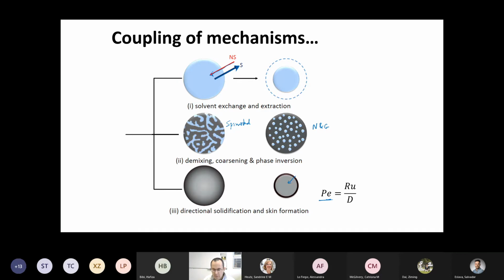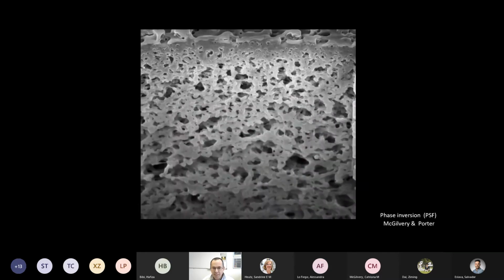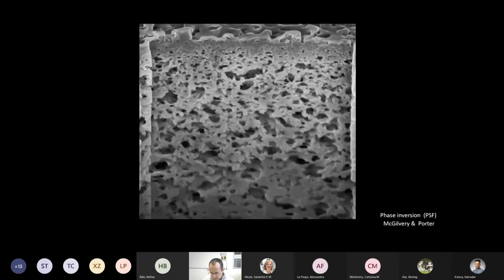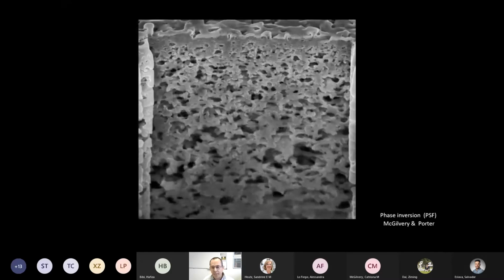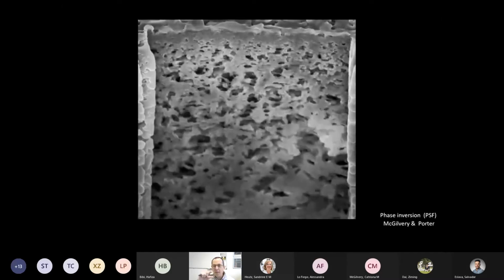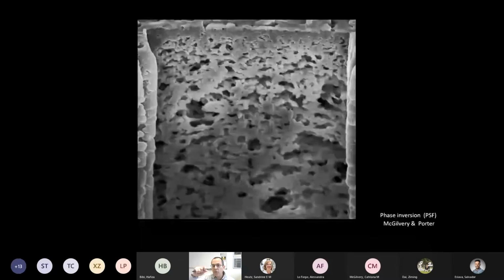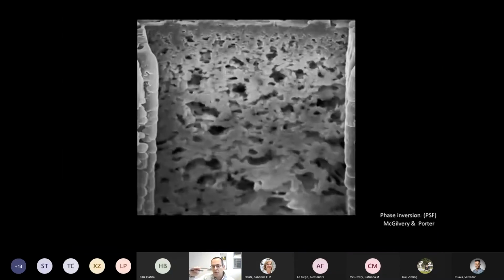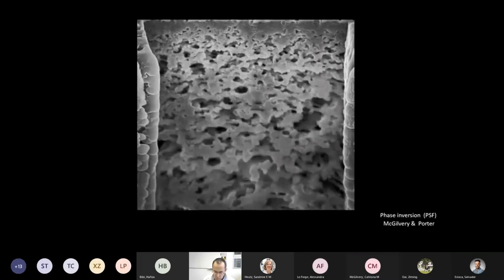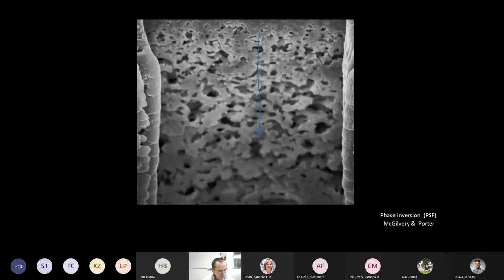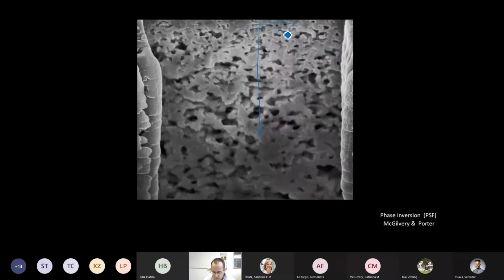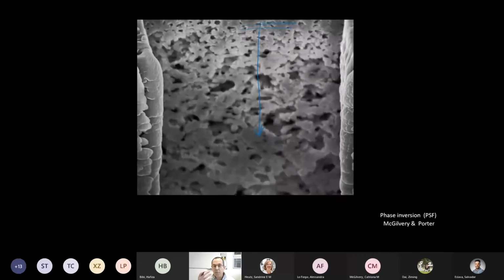And so clearly at least three processes might be at play, and they clearly will interact with each other. I think Katrina has joined the meeting, so I can show a video of hers that describes this quite nicely. This is a FIB SEM that Katrina took on a flat sheet membrane that has been produced in just the same way, but in a planar geometry through phase inversion. And so the gradient that I mentioned is this. You have a skin that is denser at the top, and then it's more open at the bottom.